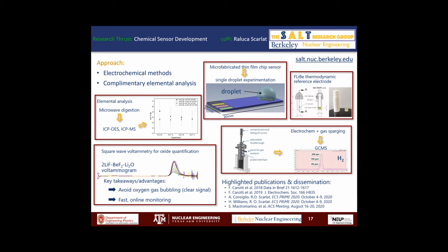Raluca Scarlat's group has been developing a stable thermodynamic reference electrode for the electrochemical analysis of FLIBE. They use square wave voltammetry to quantify oxide. As you know, the avoidance of oxygen gas bubbling will enable a clear signal, and the application of fast pulse makes the technique well suited for online monitoring.